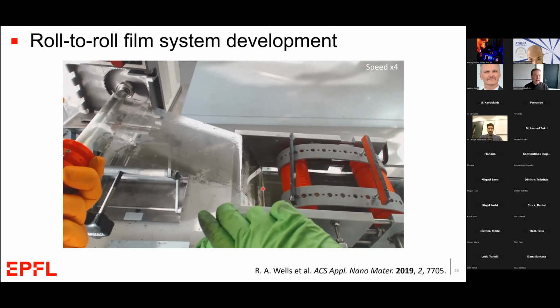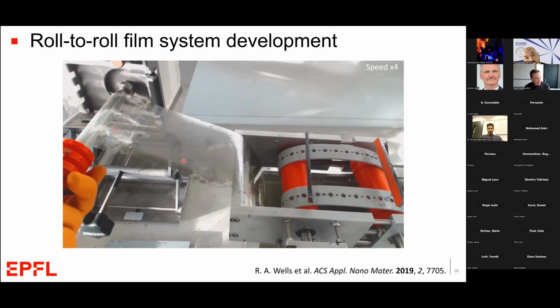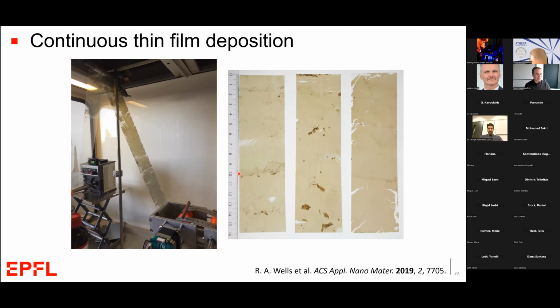ITO-coated PET substrates and show that the film that we make has similar performance to the small-scale films on glass. It's not perfect. If we wanted to optimize this and machine it better, we could get rid of some of these cracks and defects. But I think for a first demonstration of large area roll-to-roll processing with this step, we have definitely achieved that.